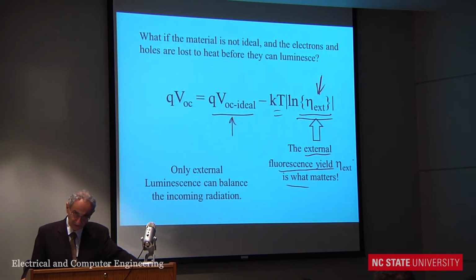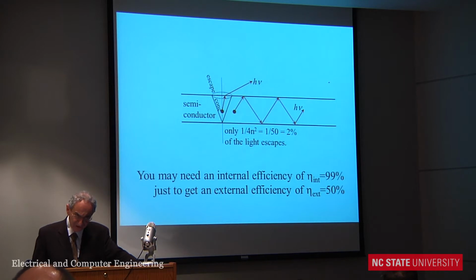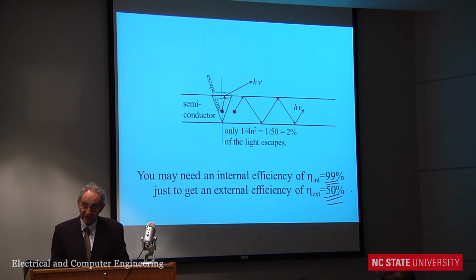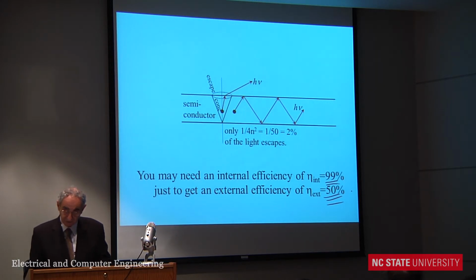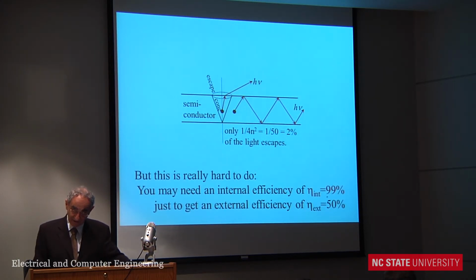It's very surprising. And this tells us how to get a high voltage: get a good external luminescence. But it's hard. The reason it's hard is the escape cone is so narrow. Indeed, because you're constantly recycling, you might need an internal efficiency of 99% just to get the 50% out, because it's going to be reabsorbed internally many times before it gets out. So this is really hard to do. Wow. 99%, and it just gives you 50% external efficiency. So it's very hard to do that.